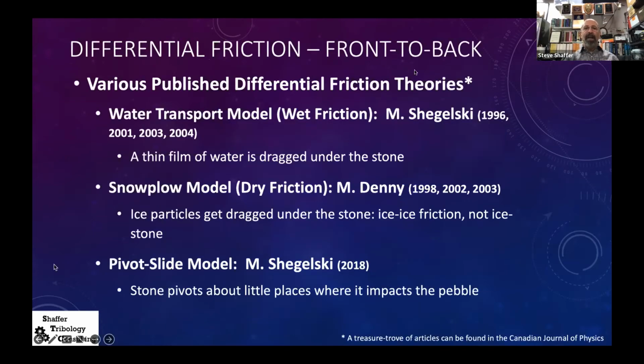Then there are these different front to back theories, and there's a treasure trove of articles. If you look in the Canadian Journal of Physics by these two authors, Shegelski and Denny, they've been at it for a long time, at each other for a long time. There's the wet friction model of Shegelski, where he says a thin film of water is dragged under the stone. More recently, he's got the pivot slide model. And then you've got the snowplow or the dry friction model of Denny, where ice particles, and we saw they're broken off, definitely get dragged under the stone, and therefore it's ice friction and not ice stone friction. There's lots of debate that goes on here, and it may be that there's some contribution from all of these. I leave it to you guys to get these papers and read them for yourself.